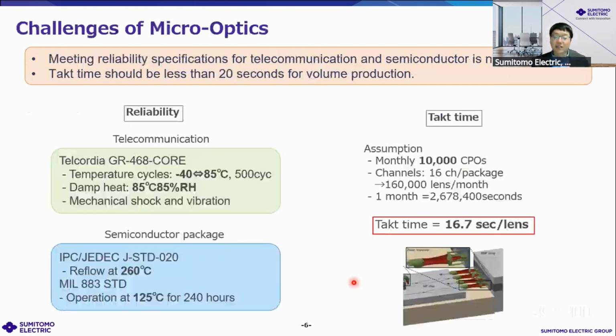Finally, I will talk about the challenges of micro-optics for mass production. One of the challenges is reliability. For CPO, we should comply with two types of reliability specifications. One is for telecommunication, so long-term reliability is required, such as temperature cycling, damp heat, mechanical shock, and vibration. And another requirement is for semiconductors, and the severe condition for packaging is required, such as 260 degrees C reflow. So we have already demonstrated that the 3D printed lens can satisfy these specifications.